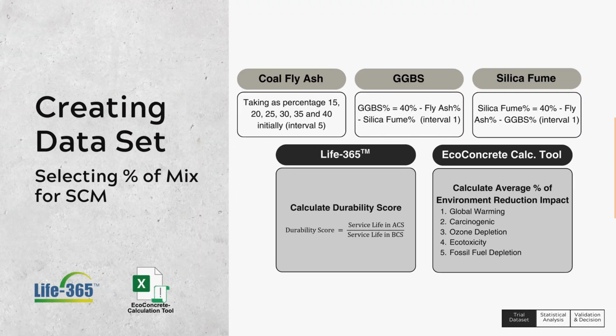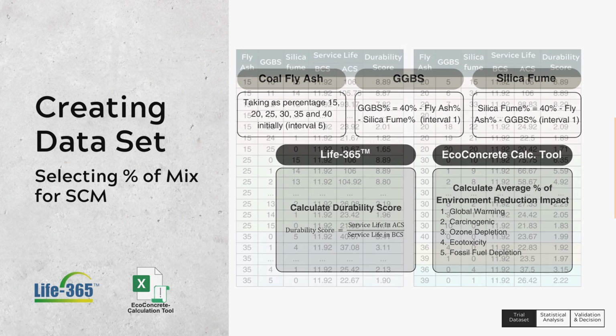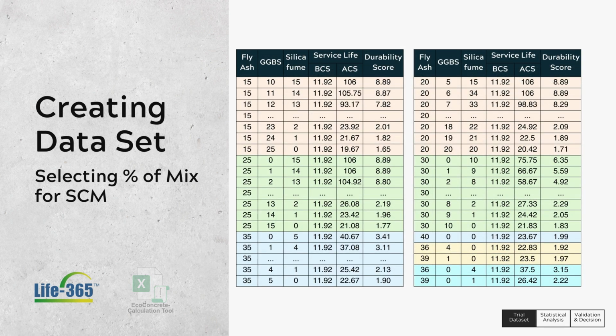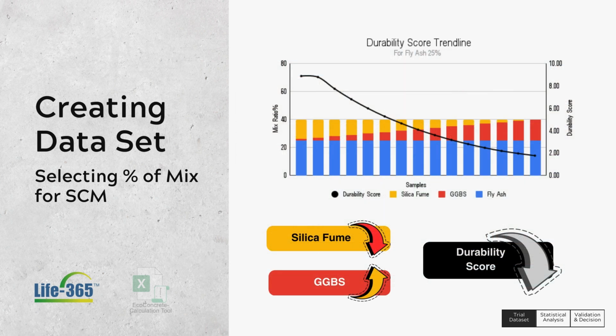We explored a wide range of percentages for fly ash, blast furnace slag, and silica fume, targeting a total of 40% SCM substitution. Every combination was analyzed to determine the service life durability score using Life-365 and the environmental impact reduction using the EcoConcrete calculation tool for all alternative case scenarios. Here is the sample dataset that we found using Life-365. As we decreased silica fume and increased blast furnace slag for a specific fly ash percentage, we noticed a drop in durability, highlighting the importance of balance in SCM selection.